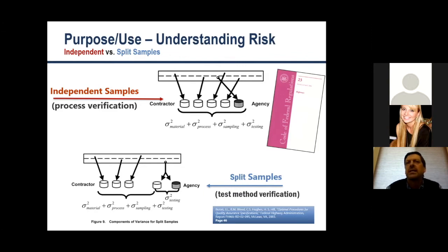Now those cores include 4 sources of variability: materials and process. I usually call that materials and construction, sampling, and testing variability. Now, if you use split samples, which is illustrated on the bottom part of the slide, same idea there. You've got a pavement, and in this case, 4 samples are taken, and the one on the far right is split into 2, right? And so in this case, cores are not a really good example of this because you don't really split cores. But if, let's say those were loose mix samples, then what happens is that split sample only really integrates testing variability. So it's not an independent sample, and